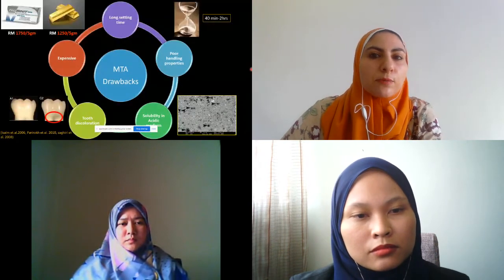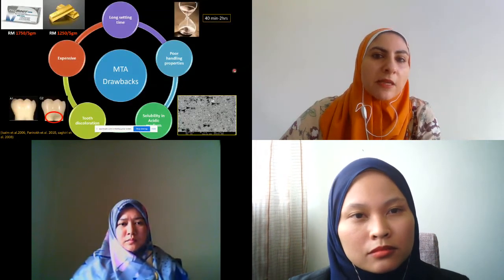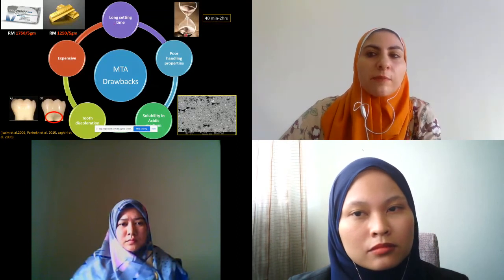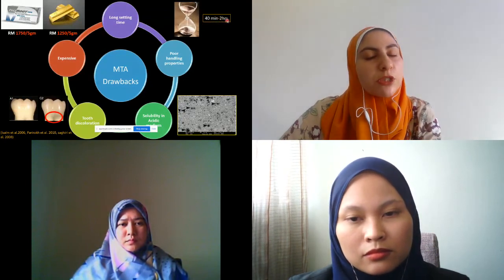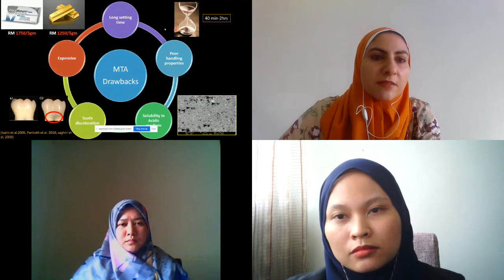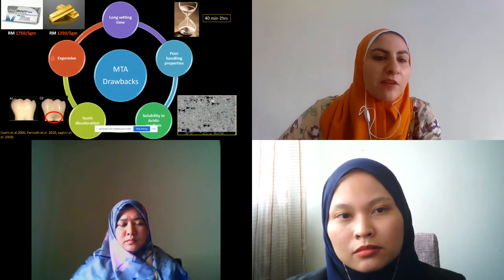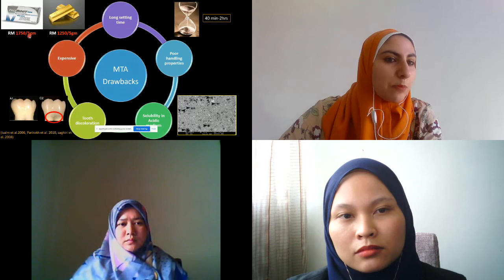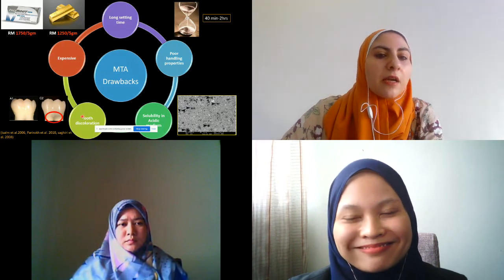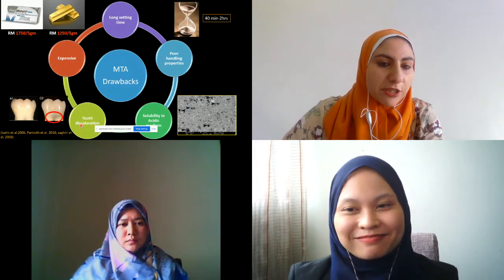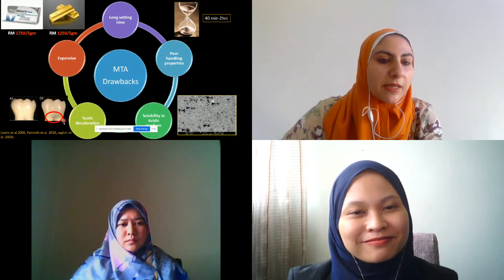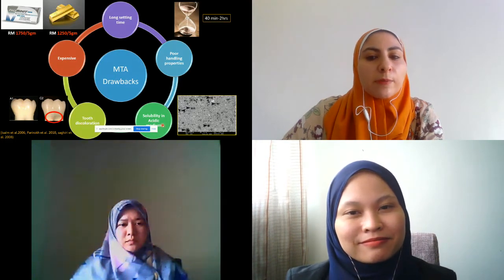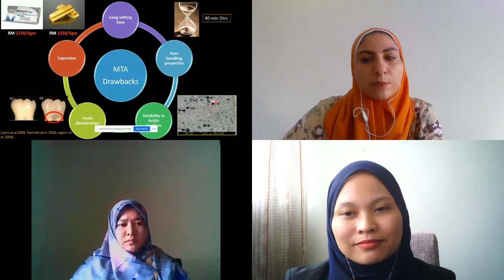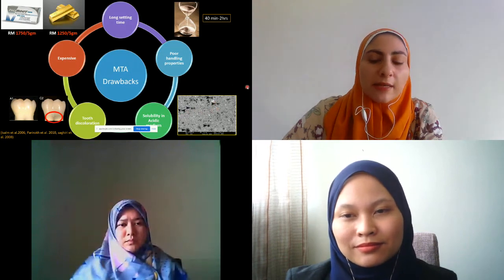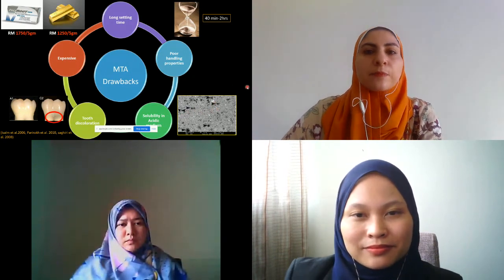So MTA is a good material, but it has many drawbacks, like a long setting time, which can be up to 40 minutes to 2 hours, which is too long for our dental visits. It is quite expensive, as you can see. It's more expensive than gold. It causes tooth discoloration, even the white MTA, as can be seen here. It is soluble in acidic medium, causing these porosities, and it has poor handling properties, just like sand.